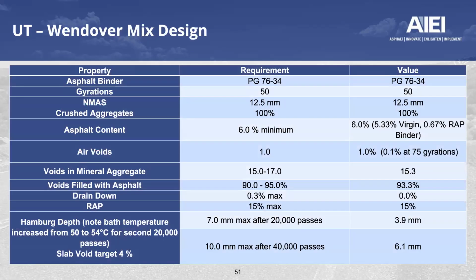The mix design requirement for the Port of Wendover, again, was at 50 gyrations. We can see the results of the Hamburg both after 20,000 at 50 degrees and then subsequently an additional 20,000 at 54 degrees. And you can see on this particular mix, even after those full 40,000, we were just a little over 6 millimeters of rutting. The VMA on this was at the 15.3, fairly close to the lower limit. Those who are involved with mix designs, that's probably not a big shock that we would be close to that lower limit. The voids filled with asphalt then winds up a little bit over 93%.